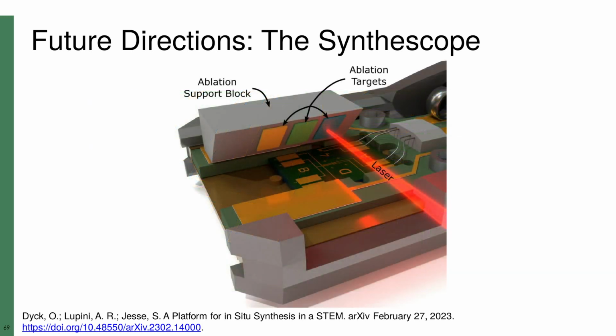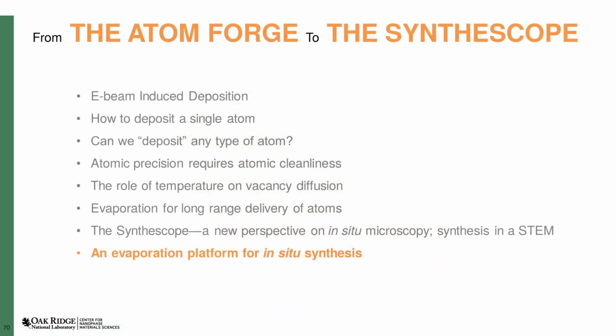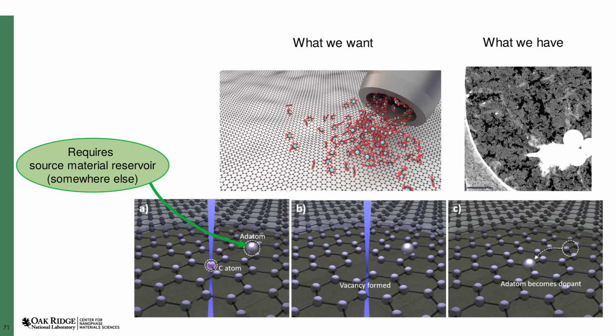An alternative strategy could be to perform in-situ pulsed laser deposition. In this concept drawing, we have multiple evaporation targets, and the laser could simply be aimed at whichever source material we want and allow us to switch materials on the fly. I am happy to report that we do not just have drawings. We have in fact built a prototype evaporation platform on which those drawings were based. The evaporation platform is an attempt to address this step of our atomic deposition process.